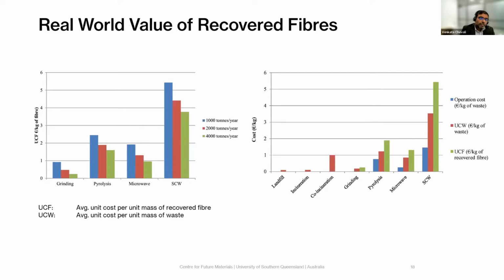So with variable recycling capacities, what you would see is some of the methods have a higher rate of producing recovered fiber and thereby the recovered cost. And that really means that you can apply a recycling method that is financially viable, even if you're, let's say, changing your business model to include recycled fibers and you're trying to replace the pristine or virgin carbon fibers as well. And as you can see on the right, in terms of the amount of recovered cost, or what cost goes into the waste, you would see that there is almost zero return for landfill and incineration, whereas there is a little bit of cost recovered in terms of the grinding, pyrolysis, and other types of recycling methods as well.